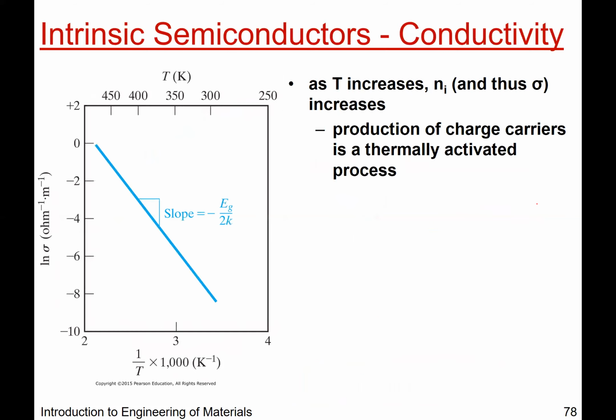And thus, if it's an Arrhenius type relationship, if you plot the natural log of conductivity as a function of reciprocal temperature, 1 over T, you see that it looks exactly like the diffusivity problems that we discussed in the diffusion module. Or rates of oxidation, things like that, they're all thermally activated. So then you can calculate what the band gap is by taking the slope of the line that you have.